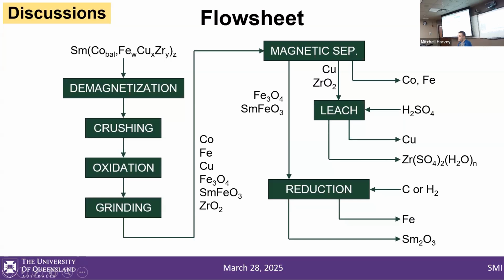Our weakly magnetic fraction, the magnetite and the samarium ferrite, we then send forward to a selective reduction step. Samarium is very difficult to reduce, whereas iron is fairly easy to reduce. As Courtney was saying, we discovered the technology to reduce iron centuries ago—it's very easy to reduce.